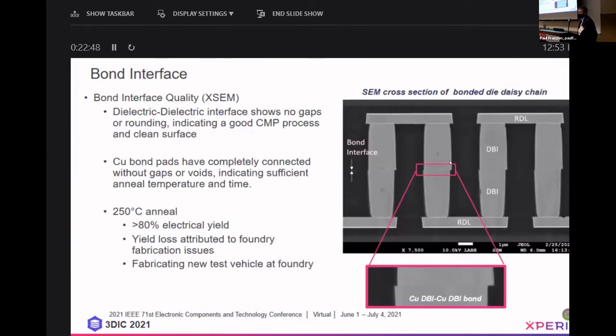This shows a cross section of the 4 micron pitch parts, daisy chain. And we can see that the dielectric to dielectric interface shows no gaps, which might be caused by rounding of the oxide during CMP. It indicates a good CMP process and clean surfaces. The copper to copper pads are completely connected with no gaps or voids, indicating we've had sufficient anneal temperature and time to close that and make that connection. You can see a close-up of the copper to copper interconnect here.